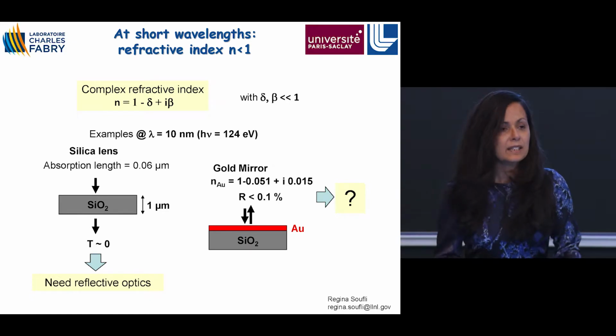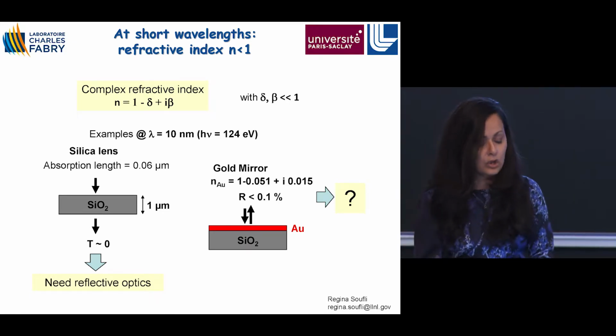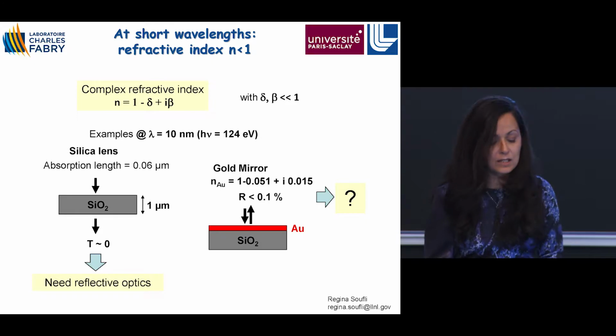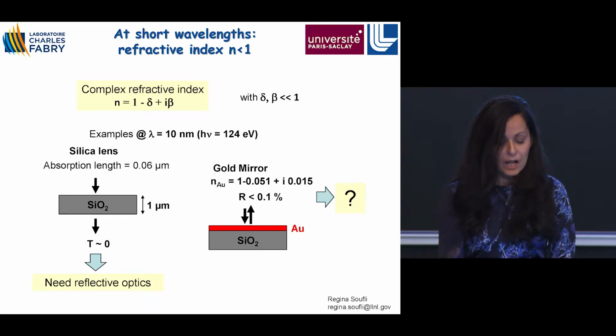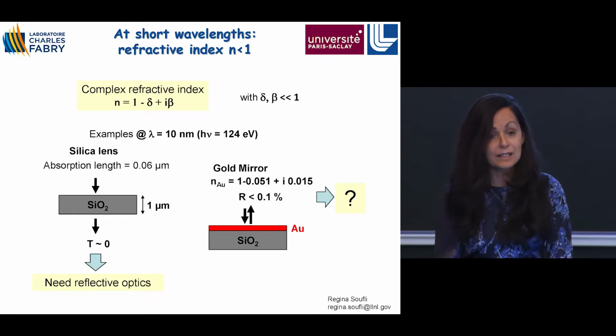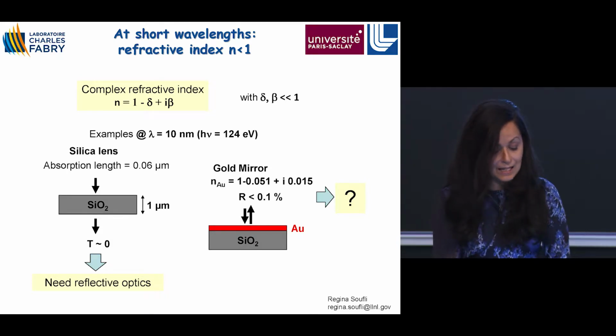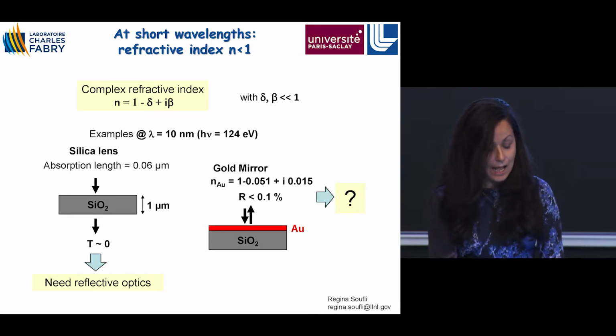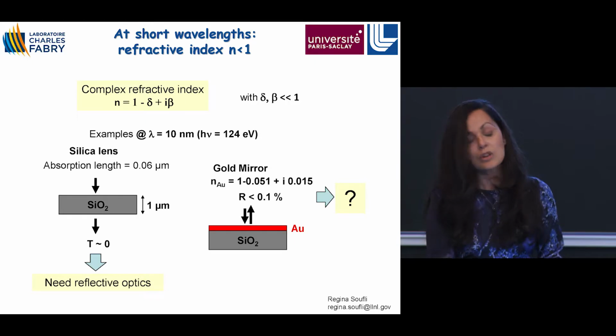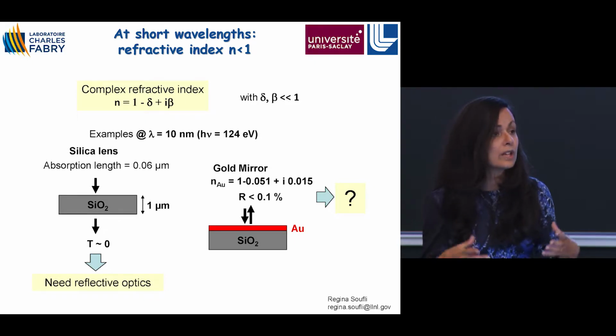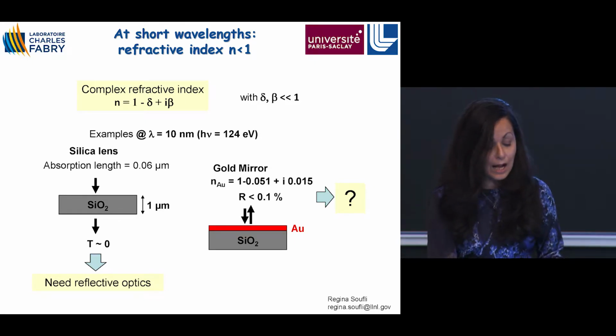So what is particular and difficult and special at short wavelengths, and why is it challenging to work in this regime? At short wavelengths, the refractive index of materials is complex, first of all, and less than 1, with real and imaginary parts that are much less than 1. So if you would like to use a lens like we use in our camera to take photos, you can't, because the transmission, if you look at the absorption length here, is almost 0. So lenses don't work. This is the first message.